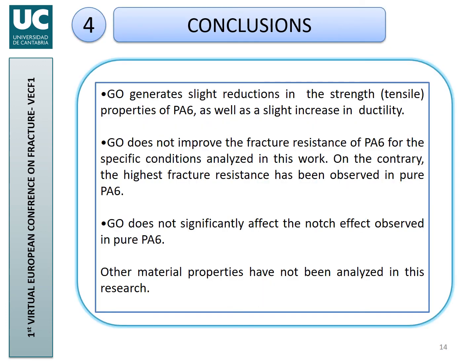So, graphene oxide generates a slight reduction in the strength properties of PA6, as well as a slight increase in ductility. Graphene oxide does not improve the fracture resistance. On the contrary, the highest fracture resistance has been observed in pure PA6. Graphene oxide does not significantly affect the notch effect observed in PA6. The sensitivity of the resulting material to the existence of notches is quite similar in the four materials being analyzed. And these conclusions are restricted to tensile and fracture properties. Other material properties have not been analyzed in this work.